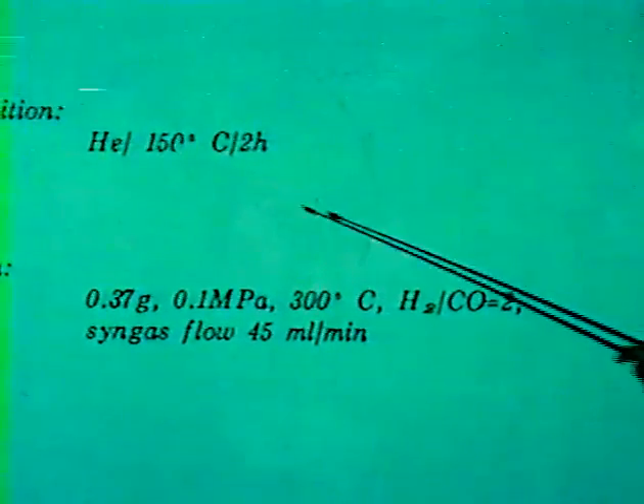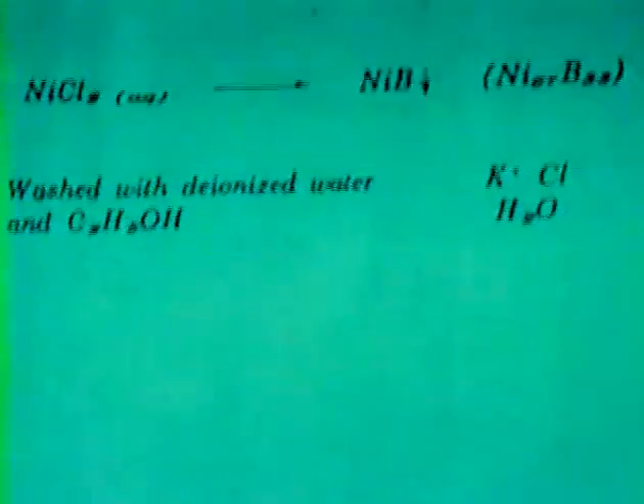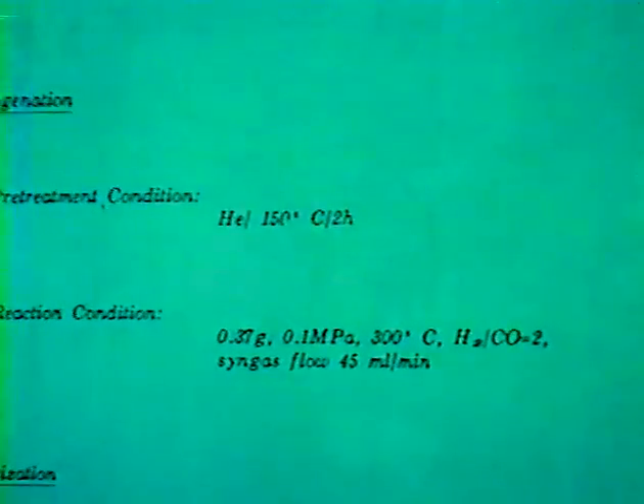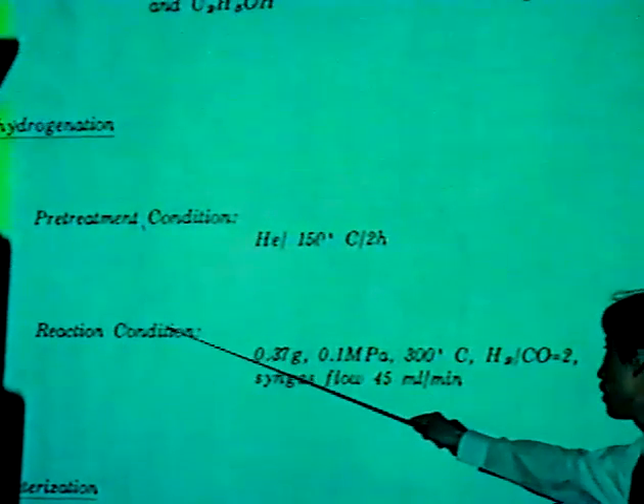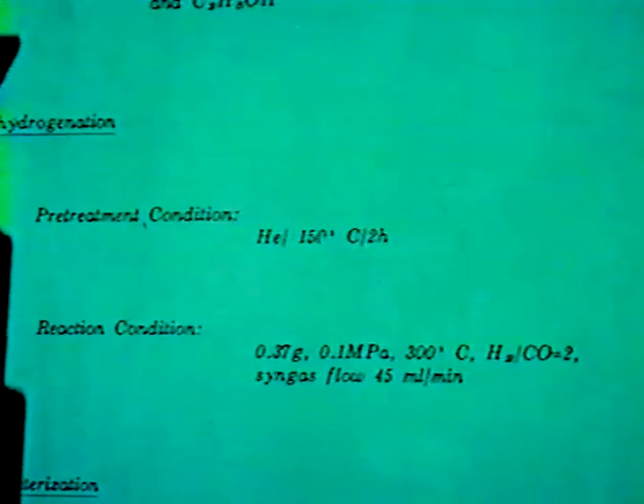Then the sample was transferred to the fixed-bed reactor where the alcohol was displaced by helium. Then the synthesis gas was introduced to the reactor. The hydrogenation of carbon monoxide was carried out under these reaction conditions. We characterized the catalyst by using XRD and XPS.